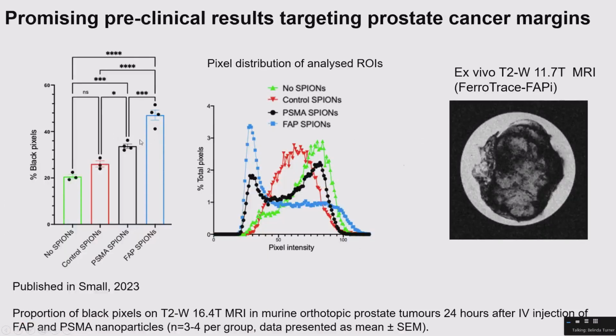And then we went to quantify the amount of contrast that was being created in these MRI images, and we assessed the proportion of black pixels in these MRI images. You can see there's an increase in contrast from the control to the PSMA and FAP. But then what surprised us again was this increase between the FAP nanoparticles and the PSMA.